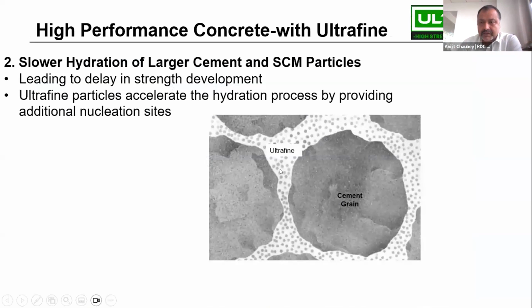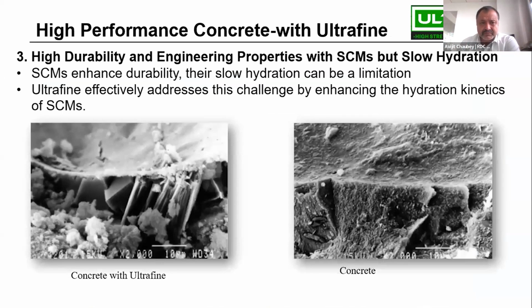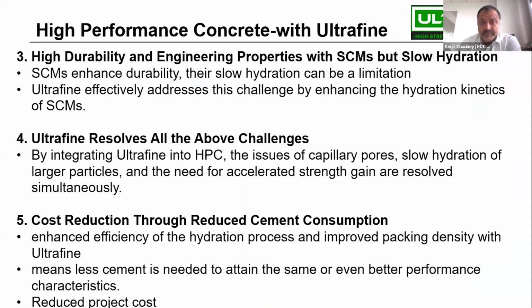Ultrafine materials are mostly 10 to 100 times smaller than cement particles, with a very high surface area. They give you good durability and engineering properties. First, because they are SCMs, supplementary cementitious materials, which are non-calcareous, mostly GGBFS or fly ash or silica-based microsilica. And you are also able to reduce the cost by reducing the cement content. If you design it carefully, you will be able to reduce the cost of concrete, and since you are able to reduce the cement, you are also able to reduce the heat of hydration and all the challenges associated with cement. And obviously one of them is the shrinkage of cement after hydration.